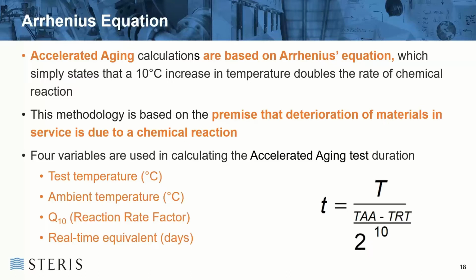Accelerated aging calculations are based on the Arrhenius reaction rate, or Arrhenius equation, as per the ASTM F1980 standard. And this simply states that any increase or decrease in temperature will cause a doubling or halving of the reaction rate, not the temperature. So if you increase the temperature by 10 degrees, it'll double the rate of the chemical reaction. And the premise for the deterioration of the material, as I said, is due to a chemical reaction. The 4 variables involved in this accelerated aging calculation are the elevated temperature or test temperature, the ambient temperature, the Q10 or reaction rate factor, which we'll look at again in a minute, and the real-time equivalent days or duration in years, and they're all plugged into the formula on the right hand side there.